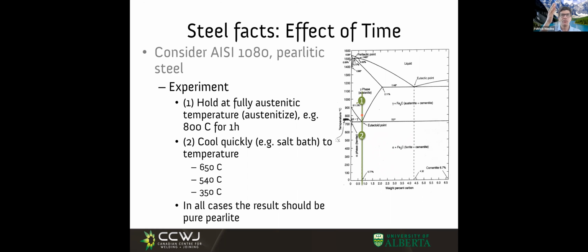Then we're going to cool very quickly, but not down to room temperature. We're going to cool down to different temperatures of my choice. The way you do this is using what's called a salt bath. If you quench in water, you essentially quench to room temperature - certainly not above 100 degrees because there's no liquid water above that. But if you use molten salt, you can do a quench that's more or less the same as quenching in water, but it's pretty hot water, right? So we're going to quench to 650 degrees, 540 degrees, and 350 degrees.